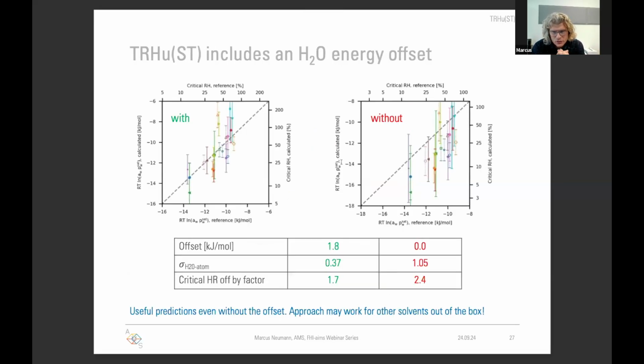There's one thing I haven't told you yet, and that is that we also fit an offset for water, but it's not as bad as it may seem. And so please first look at the plot to the right only, and that is a plot where no specific offset has been fitted. And what this plot shows you is a comparison of the predicted and the experimental relative humidities for the phase transitions. And if we would make perfect predictions, then every point would lie on the dashed diagonal. But as you can see, all the predictions are more or less under the dashed diagonal. So we are completely off to one side.